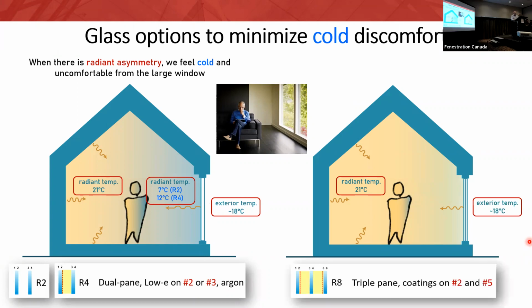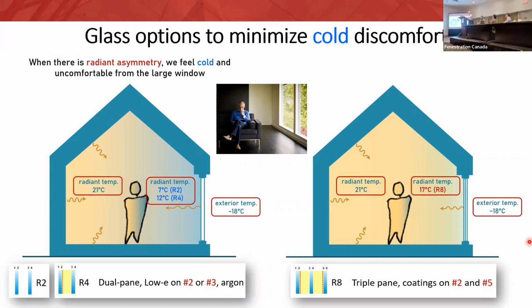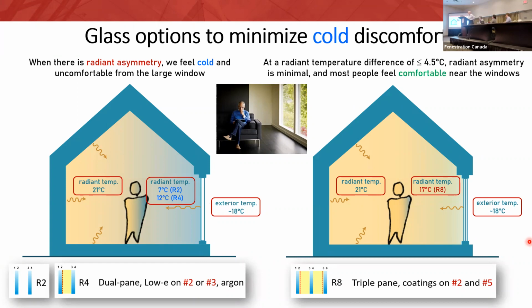Now, let's examine if you just improve that window one stage further, as we said, an R8 triple pane with coatings on 2 and 5. You now have a radiant temperature, and by the way, this 17 degrees is an NFRC number. The numbers in here are not Passive House numbers. These are NFRC numbers. Now you have a 17-degree radiant temperature from the glass, and you have a condition where radiant asymmetry is minimal, and most people would feel comfortable near the windows.